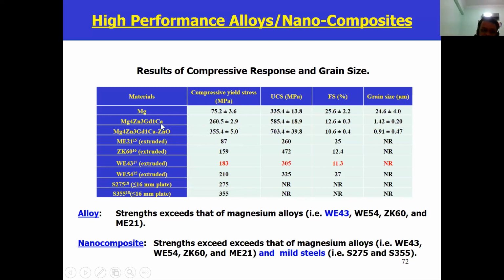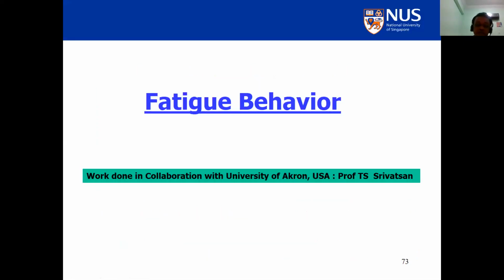And then you see the magic of nano reinforcement. You put zinc oxide in there, about 1.5%, I think, and the strength goes up to 355. UCS goes up to 703 megapascal. Failure strain stays about 10%. Grain size goes down. Now, what is the importance of these numbers? These numbers exceed not only these aerospace alloys, but also the mild steels. So that means magnesium-based materials can not only replace aluminum-based materials, but they can also replace steels, where you can get 75% weight saving. And that is where magnesium is going to come in very, very strongly.